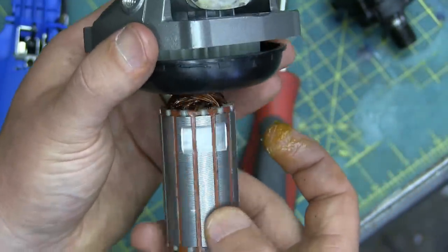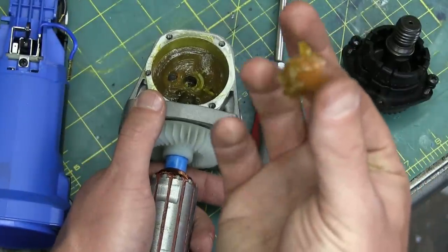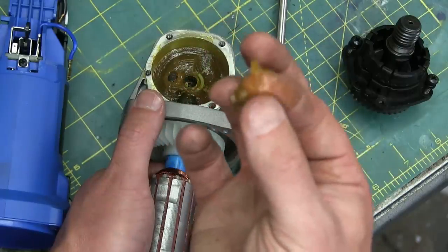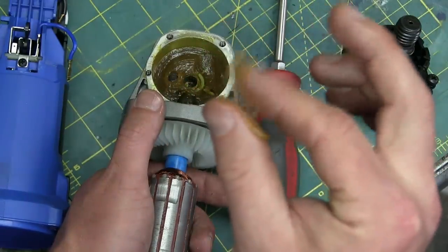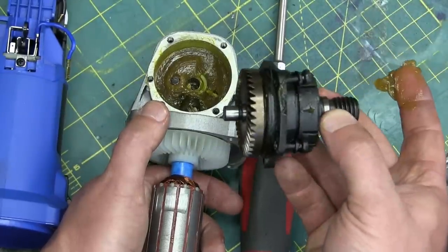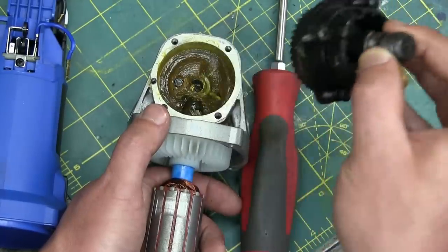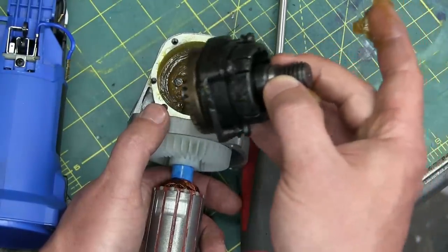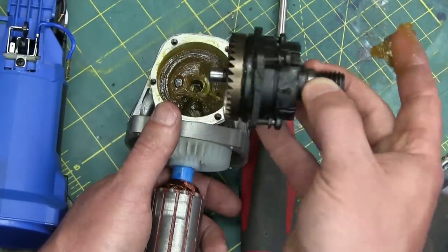The grease itself — nothing special, just cheap axle grease, just like the stuff sitting in my castor oil jug from 30 years ago. No special sticktivity. So when this gets hot, you've got hot oil next to plastic that needs to be mechanically strong — not a good thing. One thing for hot fluid in a tank designed for it where it doesn't have to be mechanically strong — but they're overlooking something here. This is definitely going to be a failure mode long term.